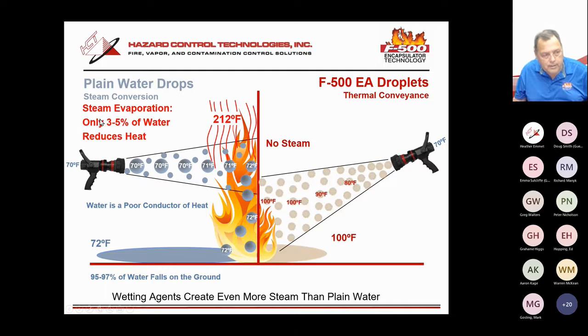So we're creating a heat sink. So here's your plain water coming out of the hose. It's coming out at 70 degrees F. The droplet, let's say 95 to 97% of it remains right at 72 degrees. The outer part, like an onion, converts to steam. You get marginal heat reduction, and you need to use copious amounts of water. With the F500, we're coming out at 70, but we're transferring the heat to the internal portion of the droplet: 80 degrees, 90, 100, 110. And since you steam at 212 Fahrenheit, and we're only at 110 Fahrenheit, we do not create any steam. We're absorbing the heat into the internal portion of the droplet.